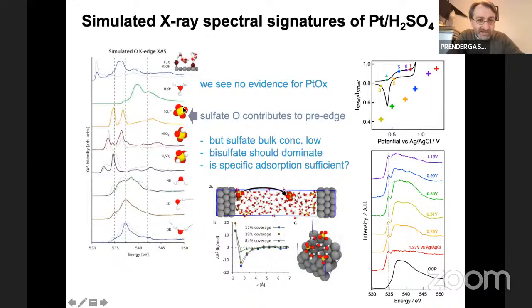And by the way, these should be tetrahedra. They look almost planar, but they're actually tetrahedra. And then the sulfate itself, which is the minor product. So even though sulfuric acid is a strong acid and it looks like it might be diprotic, it might release 2 protons, actually most of the time it exists in this bisulfate form. You have to go to pretty extreme pH to get it to remove both protons. And then the hydronium ion is the other species left.